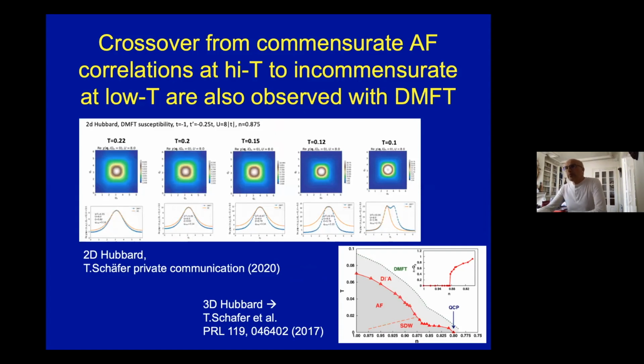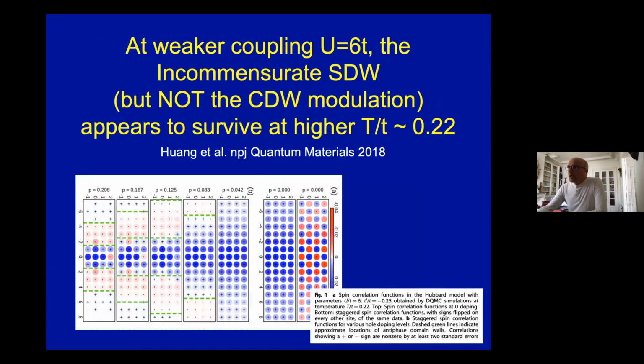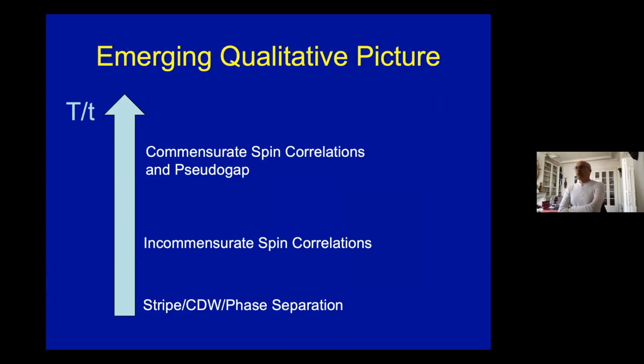This is also some work by Thomas that actually shows that as you cool down, the commensurate correlations I was talking about earlier actually do deform into incommensurate order. Sometimes this incommensurate order persists up to pretty high T, actually, such as in this work. So how do we reconcile all that?